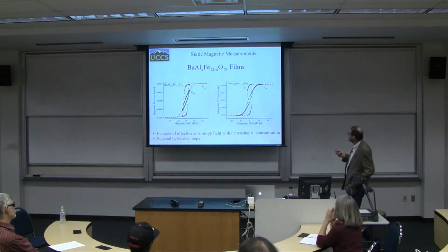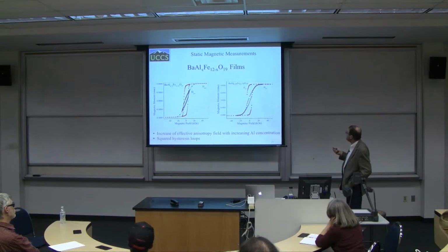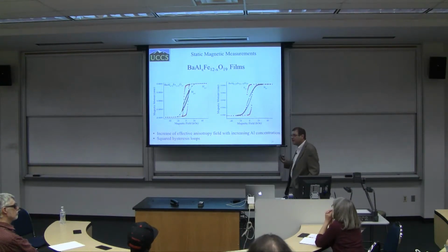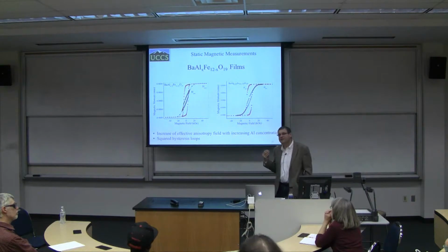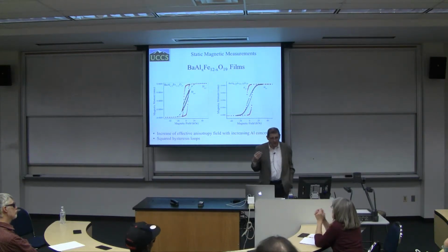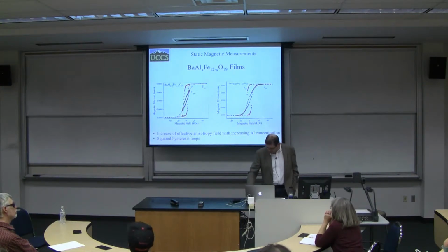Because this means that when I initially magnetize my sample and come here at 0 field, let's say here, maybe it's easier to see, I will still be almost at full saturation. And therefore my material will be stable, will not demagnetize the way other films could.